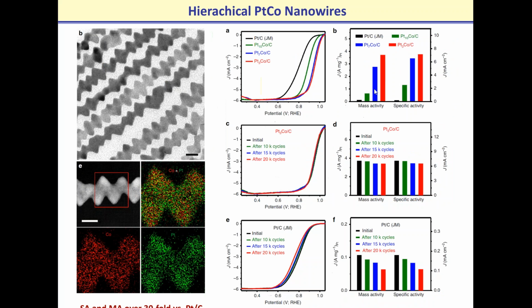Another interesting example is some type of nanowires, but you do see that zigzag type of shape. So in other words, they are utilizing in some way the advantage of having extended surfaces and flat surface morphology, but at the same time they are increasing electrochemical surface area by introducing that zigzag type of structure. So again, very high performance in terms of activity and durability as well, before and after cycling. This is a report from a research group in China.